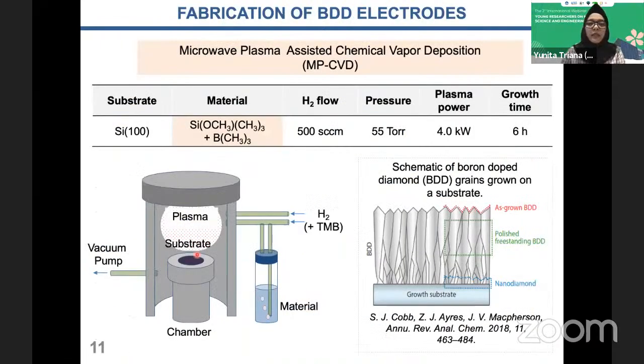We use microwave plasma assisted chemical vapor deposition, or MPCVD. We have two big machines to make the boron doped diamond. And this is the condition: the substrate is silicon, and the materials are silicon and boron. For the source of boron, we use this material, and some conditions for the preparation. So this is the scheme of how to make the BDD. This is the silicon substrate, and BDD will grow. You can see in the next picture, BDD will grow up from the growth substrate.